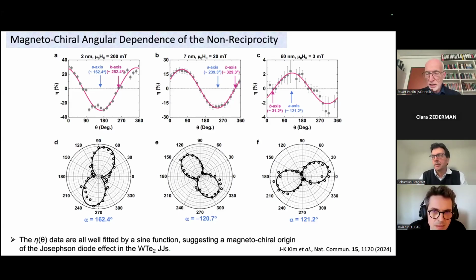And this means that we believe this is very strong evidence that the effect we're seeing is intrinsic to the tungsten ditelluride in this way. So in other words, other groups, it turns out that it was known even 20, 30 years ago that in junctions which are geometrically inequivalent, distinct for different directions, then you can basically trap magnetic flux in the junction.